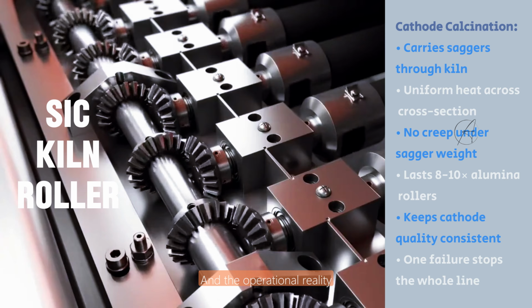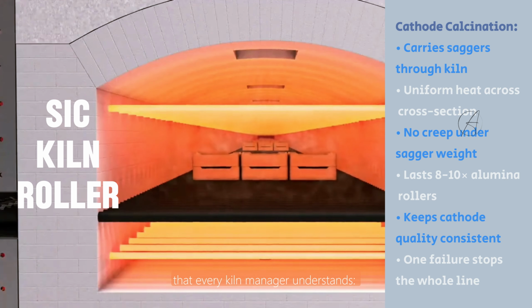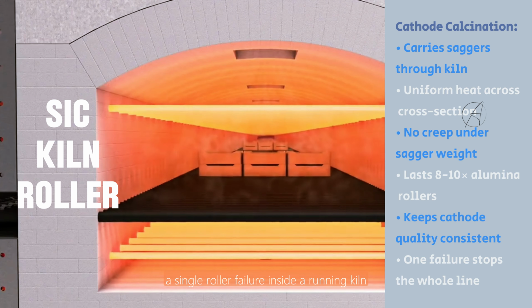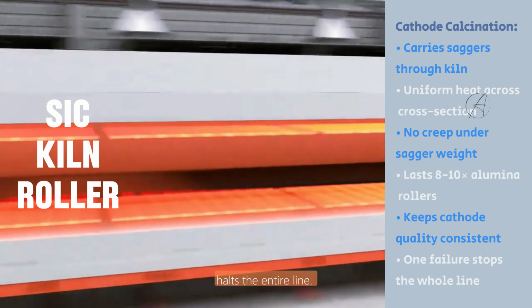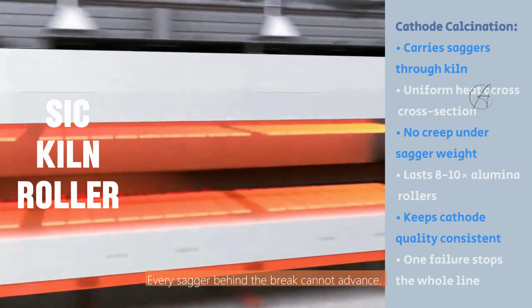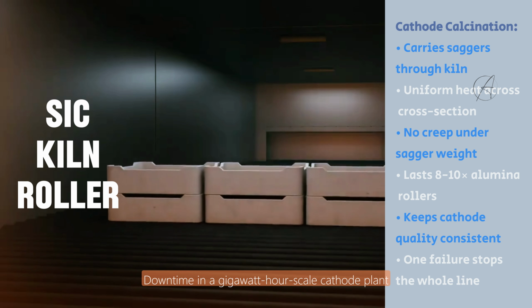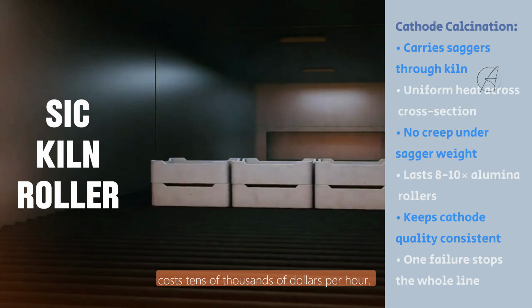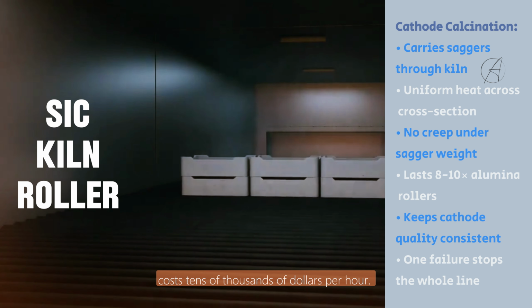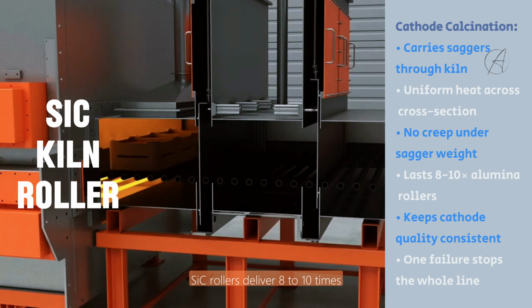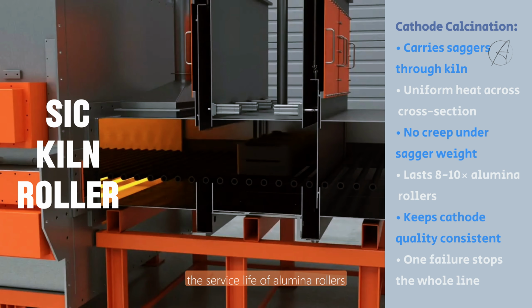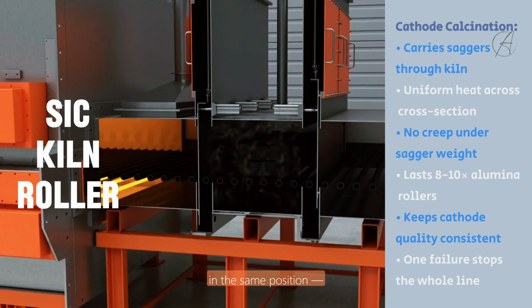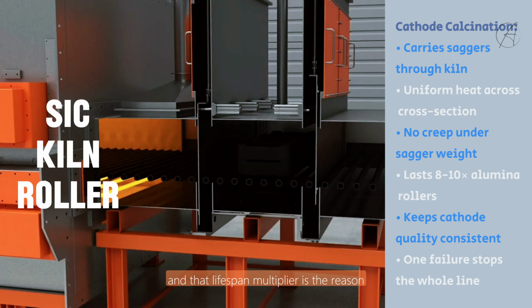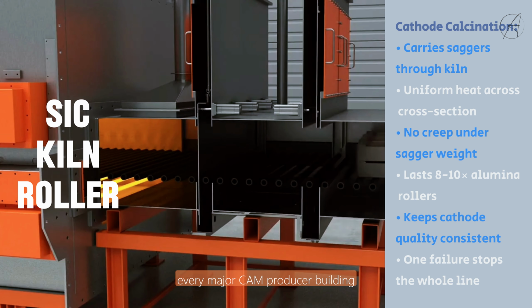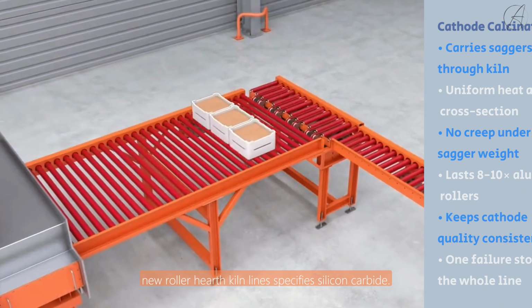And the operational reality that every kiln manager understands: a single roller failure inside a running kiln halts the entire line. Every sagger behind the break cannot advance. Downtime in a gigawatt-hour scale cathode plant costs tens of thousands of dollars per hour. Silicon carbide rollers deliver 8 to 10 times the service life of alumina rollers in the same position, and that lifespan multiplier is the reason every major CAM producer building new roller hearth kiln lines specifies silicon carbide.